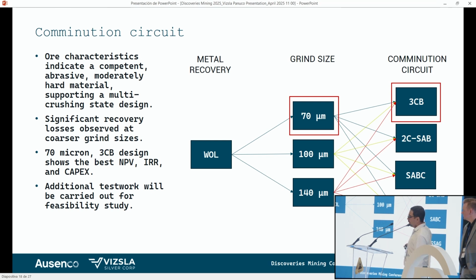So the scenarios were conventional 3-stage crushing, 2-stage crushing followed by SAG mill and then ball mill, going directly SAG mill and then ball mill, or going with a single-stage SAG. With single-stage SAG, we probably cannot get to 70 microns, but okay. At the end, we observed that the losses in recovery going coarser than 70 microns resulted in the loss of NPV.